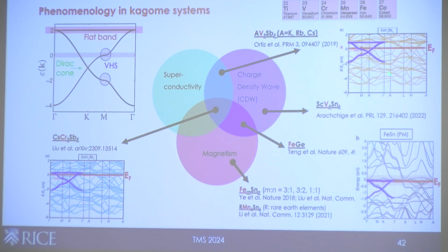So if you go from system to system, if you look at the vanadium-based, both the vanadium 135 and the vanadium 166, the Van Hove singularity, at least one of them, is close to the Fermi level, right? And these are the systems that, as we have heard, exhibit charge density wave orders. And then you keep going, and for the iron-based and also the manganese-based over here, if you calculate the DFT for the non-magnetic order phase, you will see that the topological flat bands is basically right at the Fermi level. And I'm going to talk about this in a little bit.